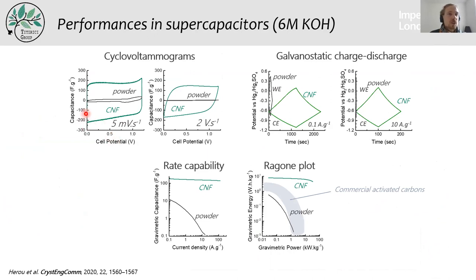So the performance in supercapacitors, you can see the distinguishable rectangular CV shape here on the left at 5 millivolts per second, which is quite a slow charging rate. And if you go a bit faster, you see that we still maintain this rectangular CV shape, and the powder doesn't show even any capacitance at this scan rate. And that is shown on the rate capability, where you can see the gravimetric capacitance on the y-axis and the current density, and we see that the carbon nanofibers maintain their high capacitance despite the high current density. And here, this is to put in perspective this material with commercial activated carbons, where usually the gravimetric energy density is between 1 to 5 watt-hour per kilogram. And here we managed to obtain 8, 9 watt-hour per kilogram, which is worth investigating more in detail.